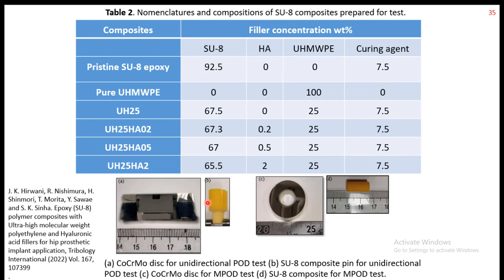The samples were made into pin form and slid against a metal part, a cobalt chrome metal surface, in a multi-directional pin-on-disc test. I will show you results with different percentages of HA, but the UHMWPE percentage was fixed at 25 weight percent, and these were also compared with pure UHMWPE.